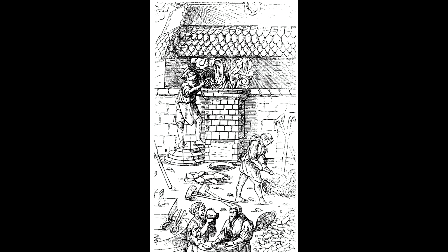Once the charcoal burns all the way down and all of the ore has been reduced, what we'll be left with is a mass of metallic iron, with some slag impurities still left, but tolerably few, in a sponge shape. In contrast to a blast furnace, which will give us iron with a lot of carbon, our bloom's carbon content will be extremely low, because the carbon that we had was burned into carbon monoxide and then oxidized into carbon dioxide, and so wasn't sticking around to be absorbed into our growing bloom of iron, which is fantastic, because we have no efficient way with medieval or ancient technology to decarburize iron, that is, pull the carbon out. So, getting iron with super high carbon counts would be really very bad. We'll talk about iron and carbon more in the last post of this series when we get into steel.